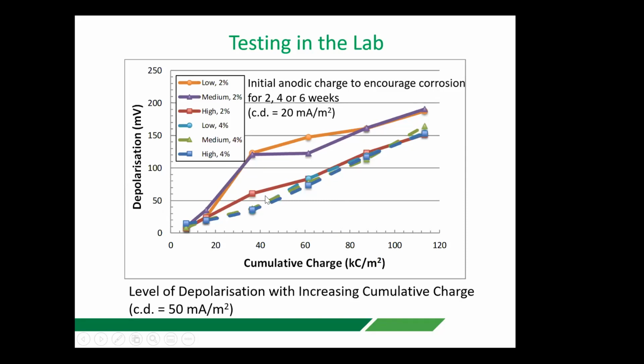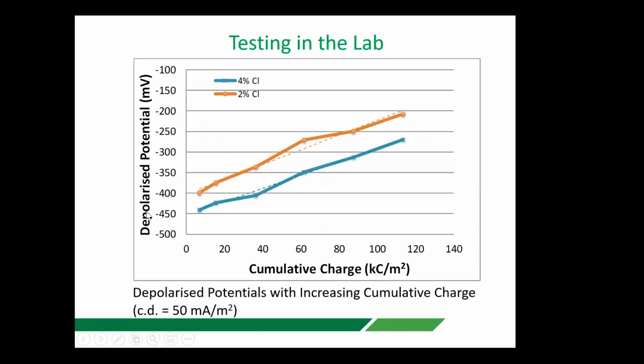But nonetheless, there was a considerable improvement every time, or rather, the higher the charge that we induced onto the steel reinforcement, i.e. the longer the application of the current, the more successful we were with our depolarization potentials, eventually achieving close to 200 millivolts. Similarly, if we have a look at the depolarized potential, i.e. the potential 24 hours after we switched off the applied current, so we allowed them to rest for 24 hours and measured the polarization potential previously, but also the depolarized potential, the rest potential.